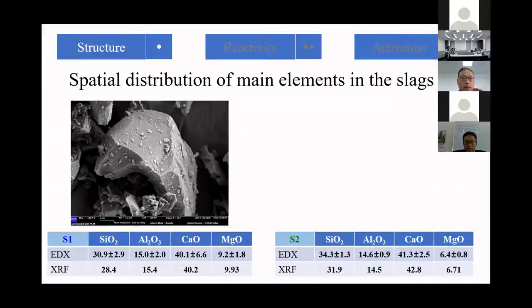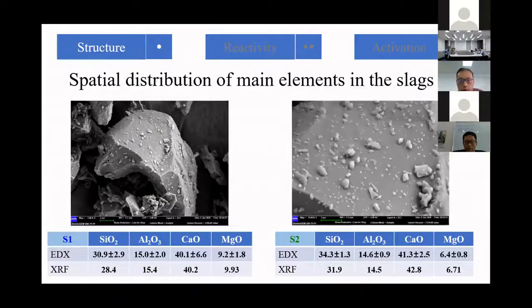The first result is about the spatial distribution of main elements in the slags. From the production of the slag, we know it's in a molten state, and this molten state can be regarded as a homogeneous state. And from our results, either the X-ray fluorescence, which gives the chemical composition of the slag in general, or the EDX spots, where the chemical composition of individual small scale was determined, comparing these two methods, we can find both methods give very similar results. So it means that the main elements distribution is quite homogeneous in slags.